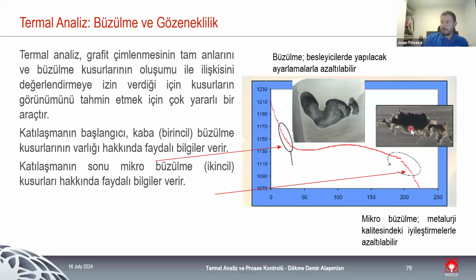And micro shrinkage, normally we can counteract it with better metallurgic control, with better carbon equivalent, better carbon silicon relationship, more control with the alloying elements that we are going to add to the melt. So there is a significant difference between macro and micro shrinkage, and when both of them happen during solidification.